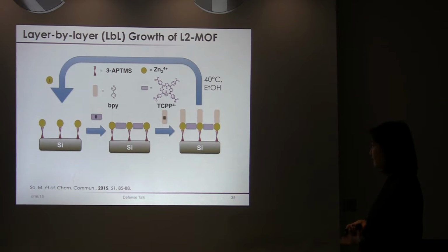And let me also remind you that I previously reported the synthesis of this L2 MOF film using this layer by layer technique. And this technique essentially forms a L2 MOF material containing sheets of this tetracarboxyphenylporphyrin that are pillared by these bipyridine linkers. And using this LBL growth, we get very good control of film thickness with molecular layer precision.